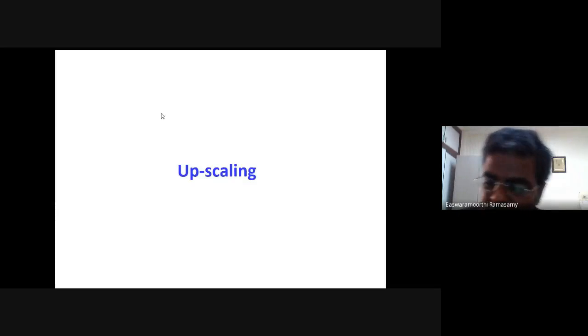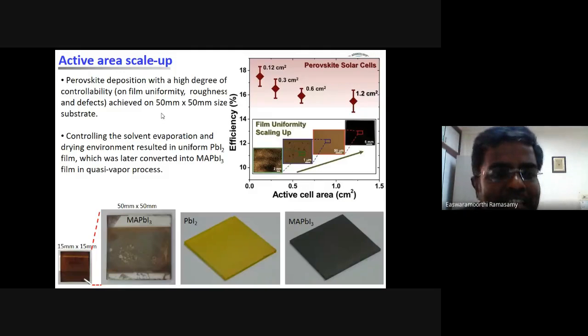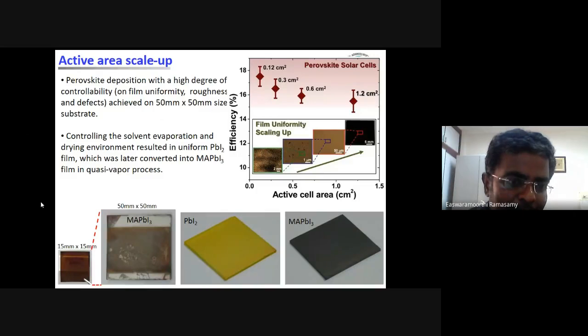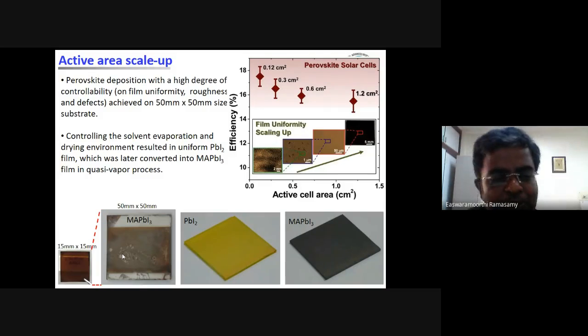So what we thought is, we have to attempt to make a large area device. We put all our efforts into upscaling the device area from the laboratory scale to prototype modules. We set 50 millimeter by 50 millimeter as an intermediate target to make the modules. You can see that if the active area of the cell is increasing, the efficiency of the cell comes drastically down. At 0.12 square centimeter, about 18%. And then for 1.2 square centimeter, the efficiency is about 15%. The reason is solution process